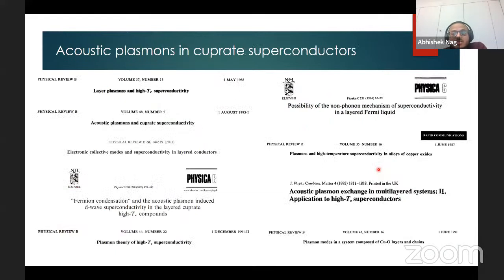So naturally, after the cuprate superconductors were discovered, several theoretical works proposed that such low-energy acoustic plasmons in the presence of coupling with phonons could also contribute to superconductivity. Unfortunately, such low-energy acoustic plasmons were not observed for over 3 decades in the cuprate superconductors.